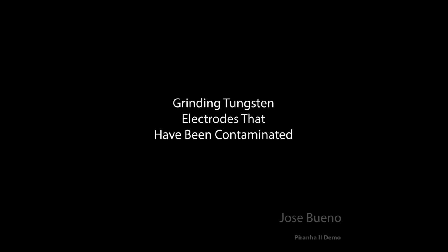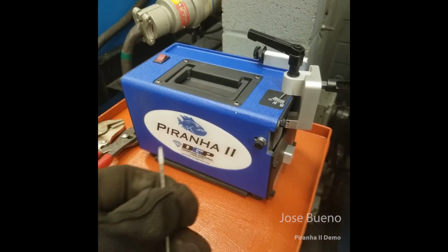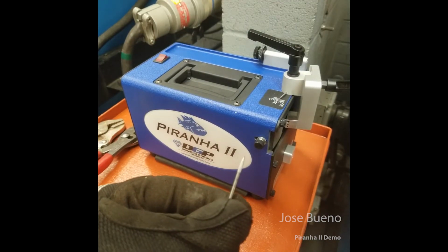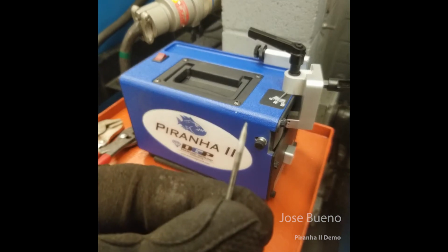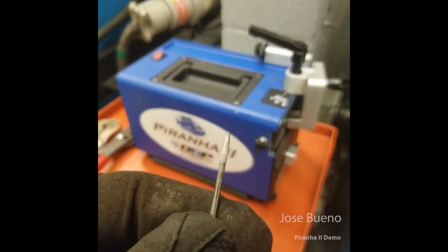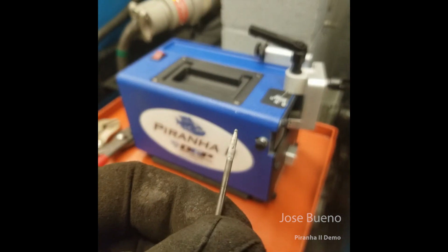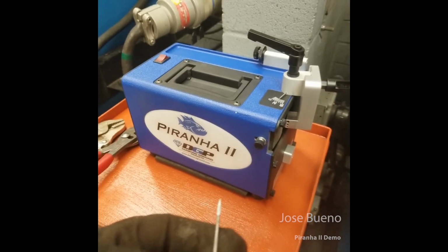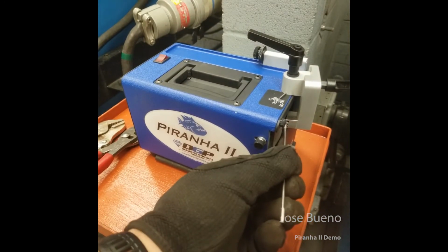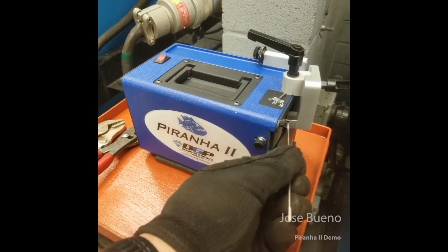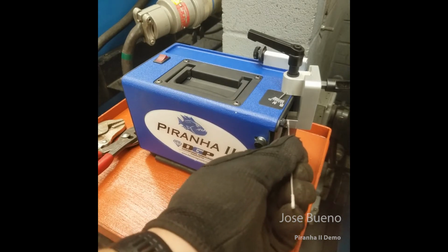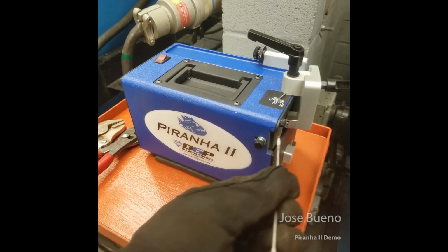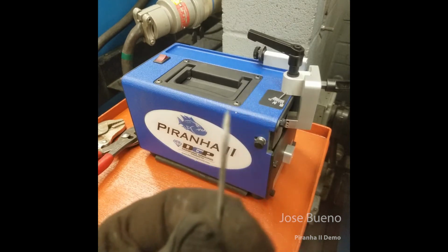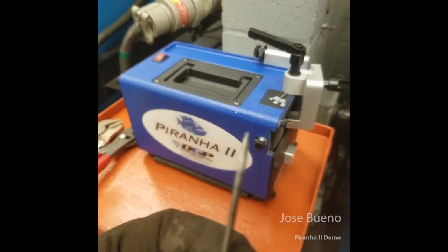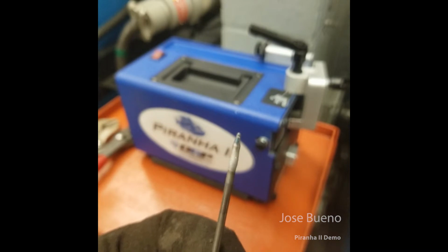Okay, so let's talk about contaminated tungsten. How do we re-grind contaminated tungsten? Well, for one, you never want to just put contaminated tungsten right into a tungsten grinder, because that's going to leave impurities in the grinding stone, which can then be transferred to other tungsten electrodes when other people go to grind them. But also, there's really no way to measure whether or not we've removed all the impurities off of our own tungsten electrodes during the grinding process.